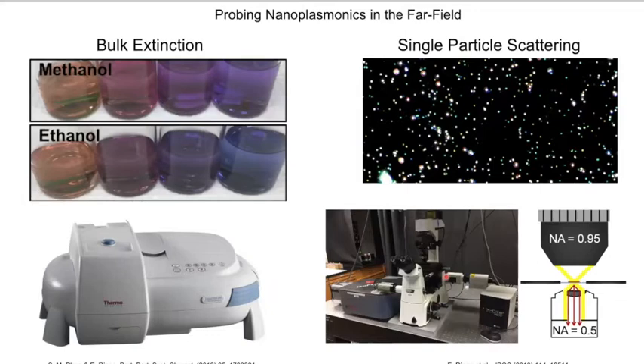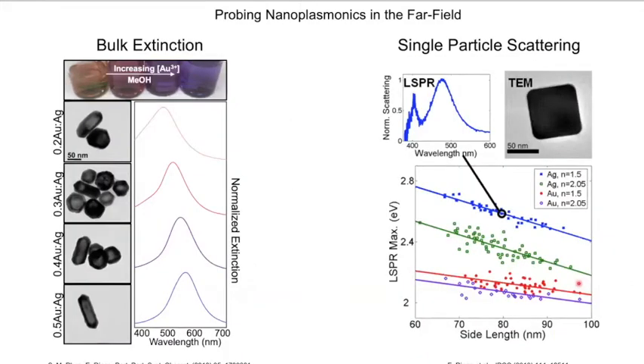So in the far field, well, you can take a UV-Vis extinction spectrum, for instance, or you can take a single particle scattering spectrum, and the way we do this is using a dark field scattering geometry where we illuminate our particles with a hollow cone of high angle light and collect only the light scattered by the particles, and it gives us these kinds of data. Okay, so on the left here are extinction spectra for different types of particles. Here the composition and the shape is what shifts the spectrum. Or we can look at a single particle and correlate that, say, with a TEM image. I've done lots of that sort of thing a decade ago now, basically looking at the size and the shape dependence of the plasmonic response.